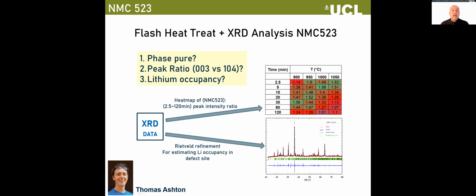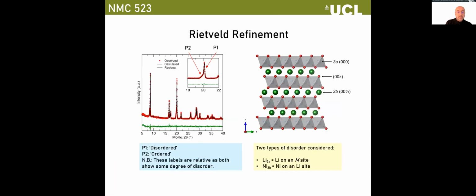And so what we've done here, from the XRD data, is look at different times and temperatures: 900 degrees C for 2.5 minutes, using our flash furnace, up to 30 minutes and 120 minutes. We've been looking at the values, and anything near about 1.2 is red. As you get further away from 1.2, it's more green or other colors or brown. So when you're looking at this, you've got something interesting at 2.5 minutes. But frankly, I'm not saying this is particularly useful unless you actually test the batteries of these materials, which is what we actually do.